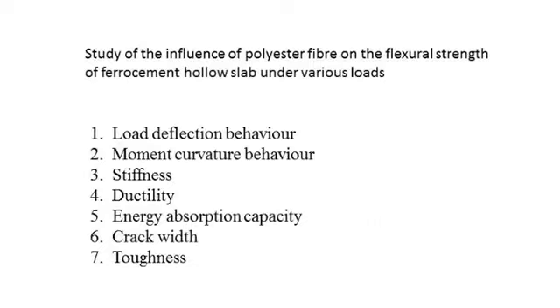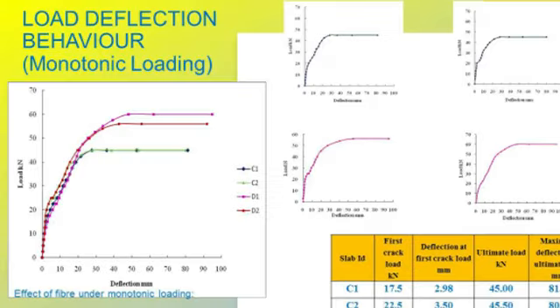And to study the influence of the polyester fibers in enhancing the flexural strength of the ferrocement hollow slab, the load deflection behavior, moment curvature behavior, stiffness, ductility, energy absorption capacity, crack width, and toughness were studied. Then this is the load deflection behavior for monotonic loading. These 2 curves indicate slabs without fiber, and these 2 are for ferrocement slabs with fiber.